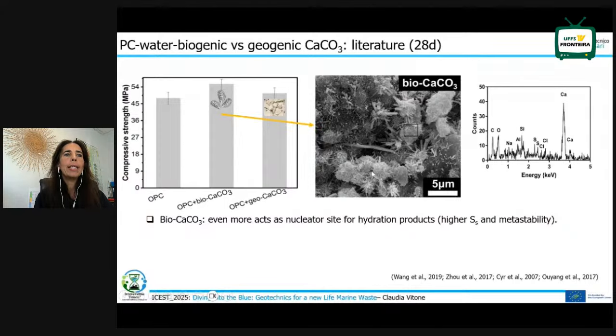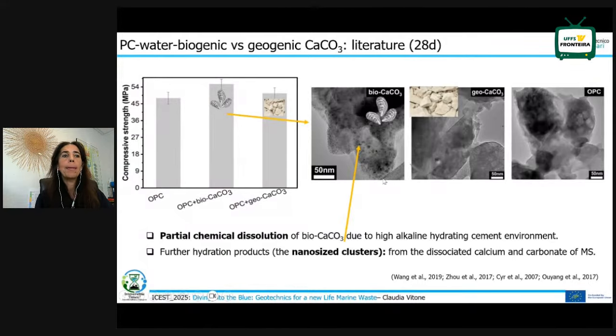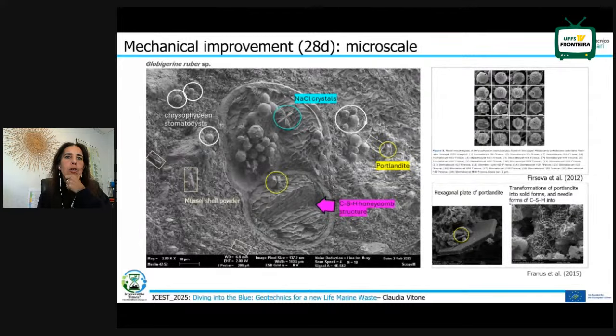observed essentially that the biogenic calcium carbonate is acting as a nucleation site for hydration products due to the higher specific surface and its metastability. And also in the TEM measurements, so at very, very big enlargements, they could also observe some nano-sized clusters, which suggest that there is a dissociation between calcium and carbonate, despite the low temperature of preparation of the mussel shell powder.